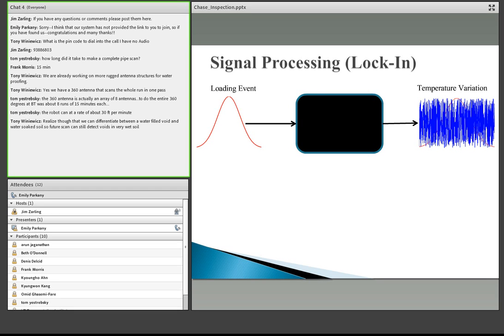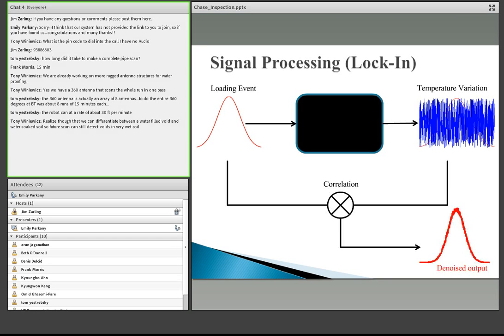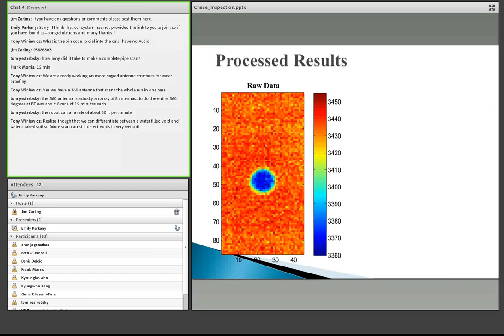In order to extract these very low signals from very high noise environments, we had to rely upon a special signal processing method called lock-in signal processing, where we used correlation signal processing to only extract information from a very noisy signal that is correlated with the loading event that produced the thermoelastic signal that's buried in that noise. And we were successful in implementing this lock-in post-processing method and capability so that we were able to extract a thermoelastic signal from a randomly loaded specimen.